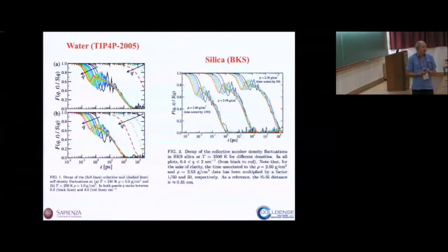So let's try to look at atomic and molecular systems. You look at water. Those are simulations with millions of atoms for a very long time, but you can still do it nowadays with graphics cards. And you calculate the collective correlation function. Again, these are distances much larger than the nearest neighbor distance. You see that the alpha relaxation time is always the same for all curves. And here, this dashed line tells you the self part, which is a clear indication that the collective relaxation decays faster than the self, which means that they decay without particle diffusion. It's a process of decay of the density fluctuation which doesn't require transport of mass in the system.